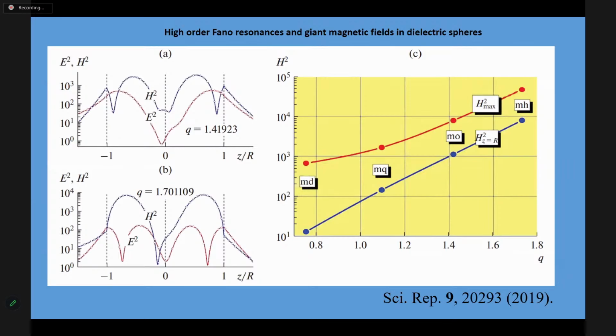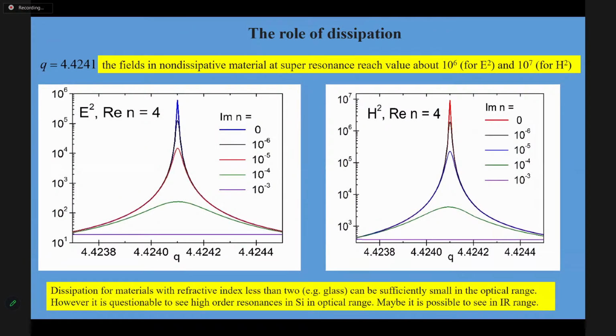And if you follow two different resonances, then you can see that the intensity of the magnetic field inside the particle increases drastically with each resonance, approximately 1 order of magnitude. However, it needs weak dissipation, like in plasmonics, we need small dissipation.